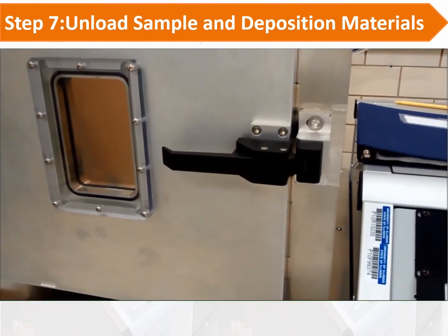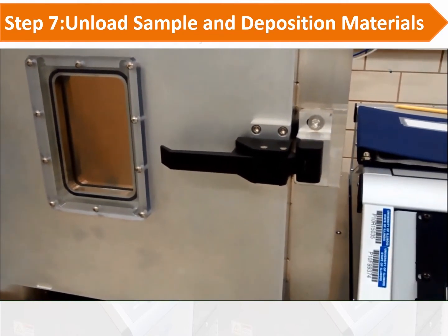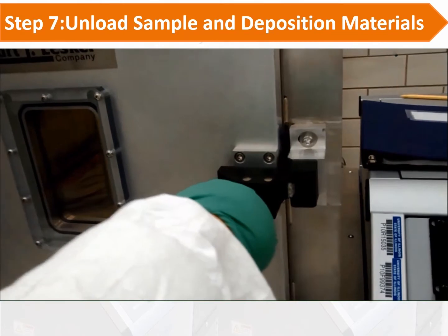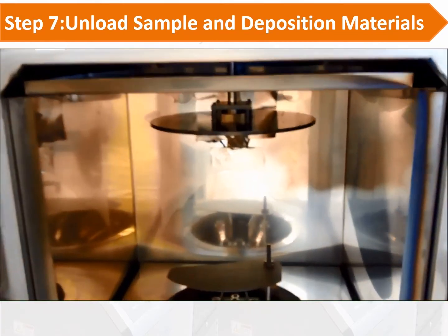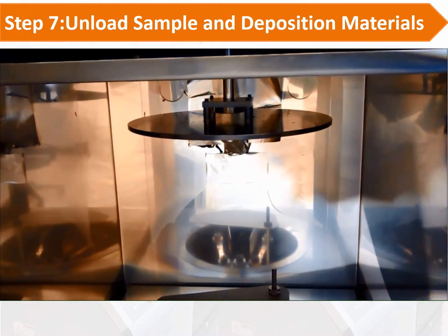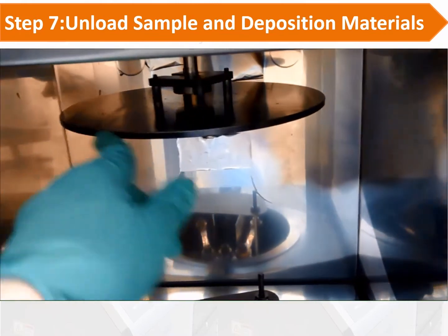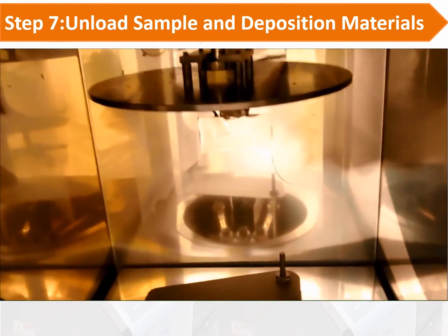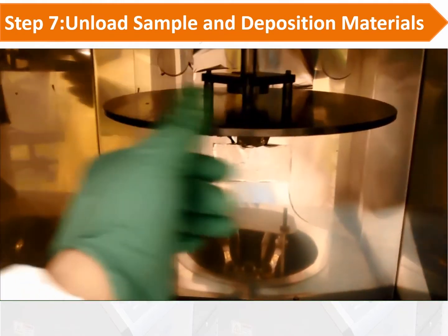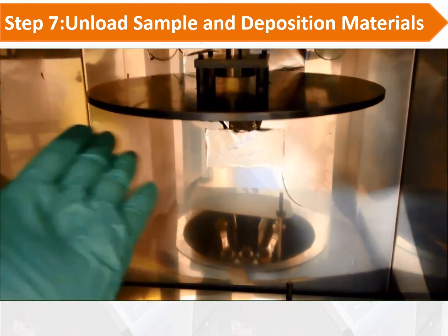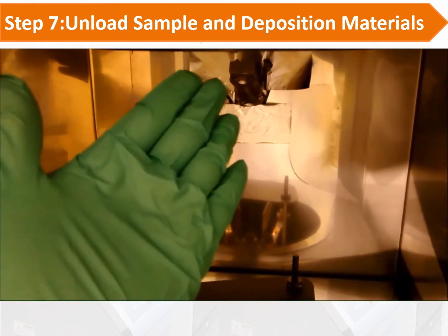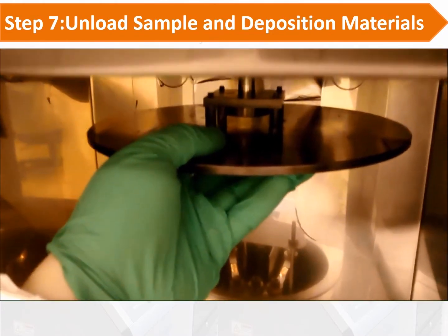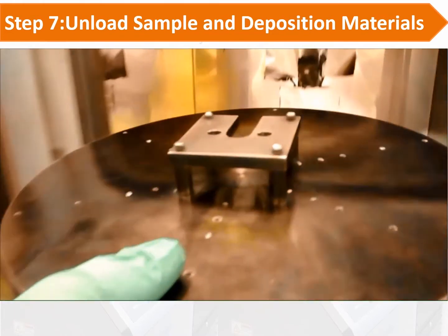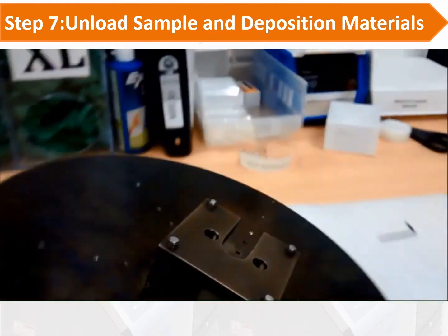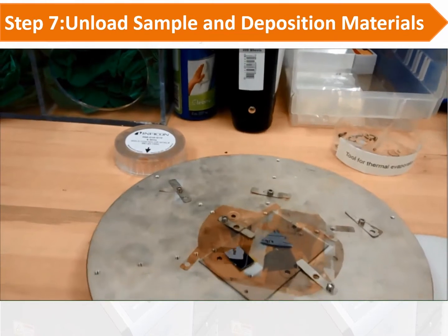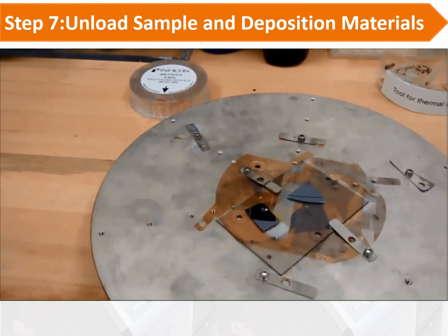Step 7, unload sample and deposition materials. We open the chamber door, and then we can unload the sample from the chamber. After the rotation, if you find the opening faces you, please rotate it and make sure the opening faces inside. This will make it easier to get the sample holder out without touching the crystal monitor. You can lift it up and grab it out. Then you can loosen the screw to get the sample out.